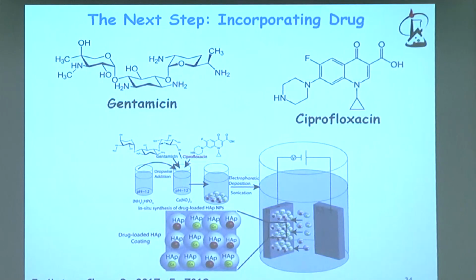And the next step means that now, because everything is done at room temperature, you can obviously add to the nanoparticles any drug you want. And in this case, we added two different antibiotics, as can be seen here, in a very simple way. You synthesize the nanoparticles, you add your antibiotics, and you actually load the antibiotics with nanoparticles.